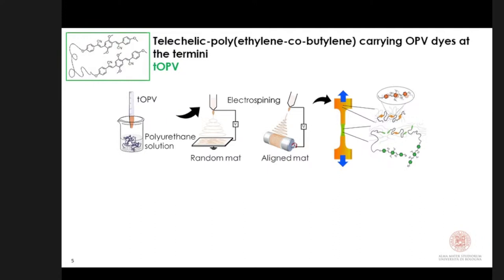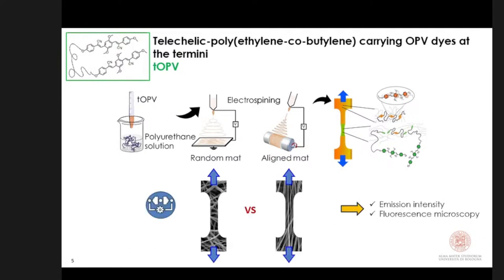With the technique of electrospinning, we were able to make these woven-non-woven materials made of nanofibers that can be dispersed with a random orientation or aligned parallelly, depending on the collector that you use during the process. So we made these two different morphologies of the material, and we tested them to study their mechanochromic response.